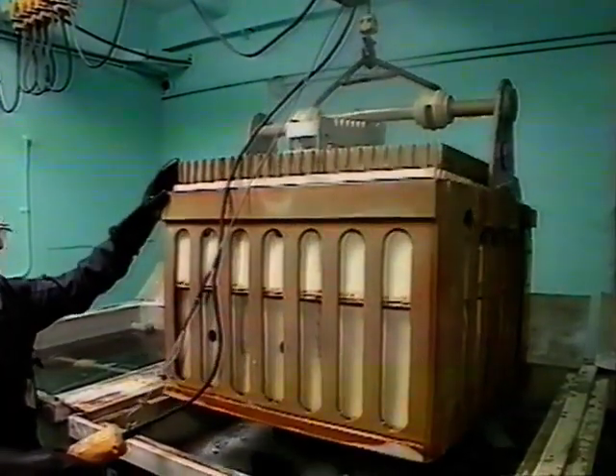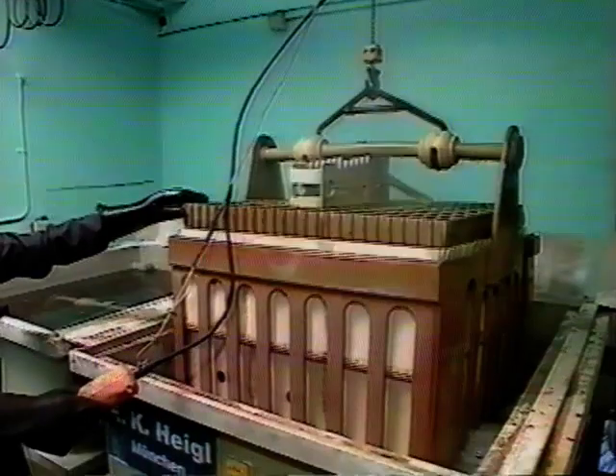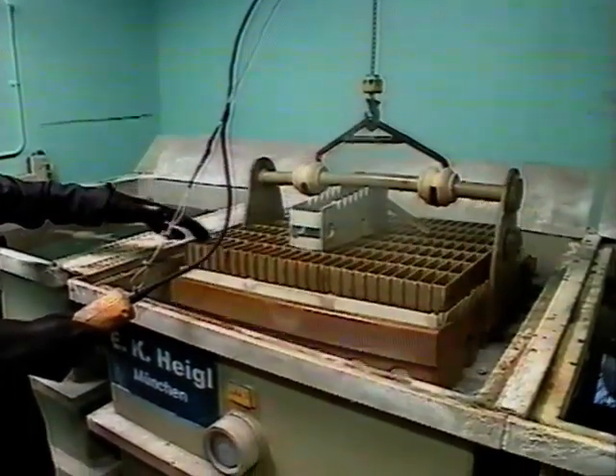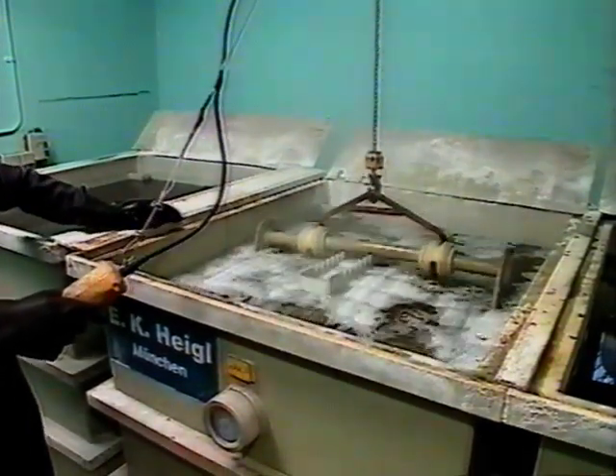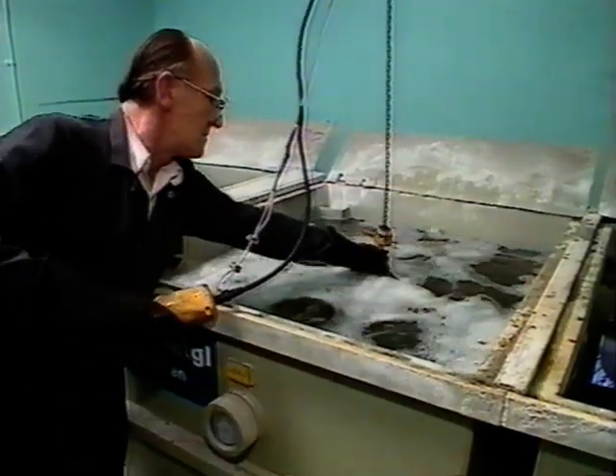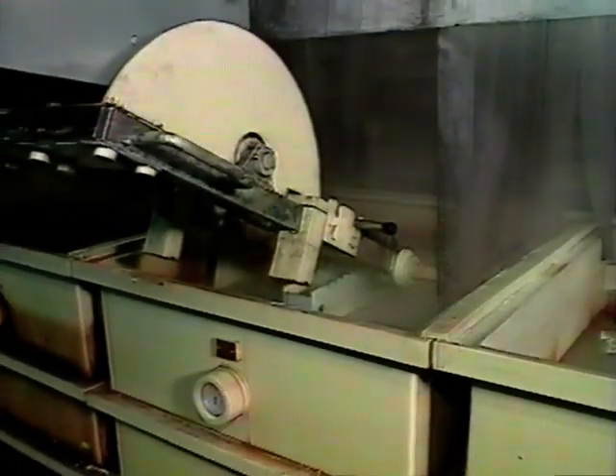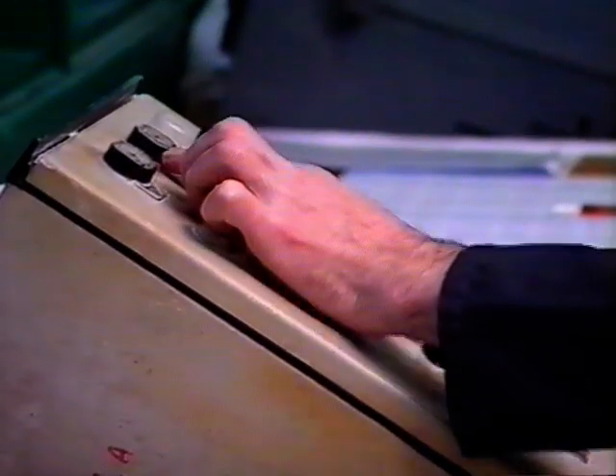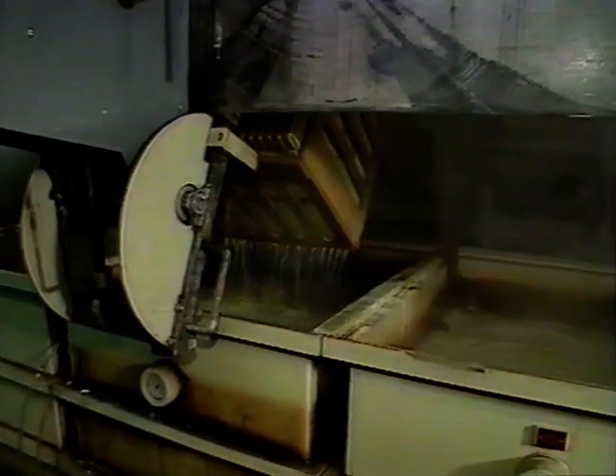The first dip is in detergent. This gets rid of any of the ink markings that may still be on the surface. Each basket load of glassware is then moved to a bath of hydrofluoric and sulfuric acids. This removes a very fine layer from the whole surface. During this first immersion, salts form on the surface of the crystal. To get rid of these, the glasses are dipped in another bath, this time of sulfuric acid.